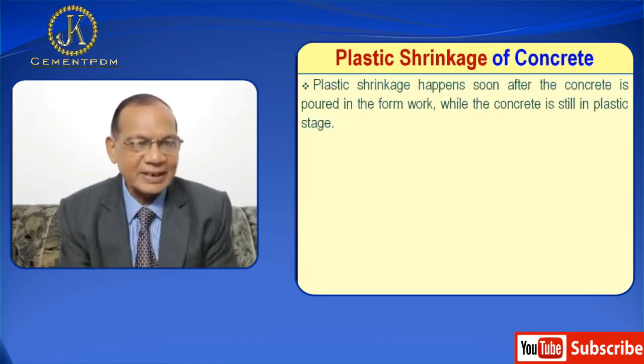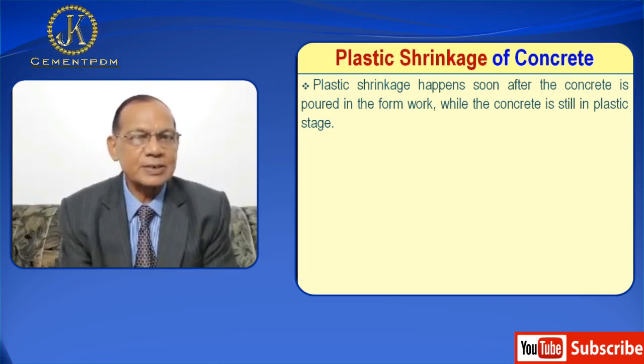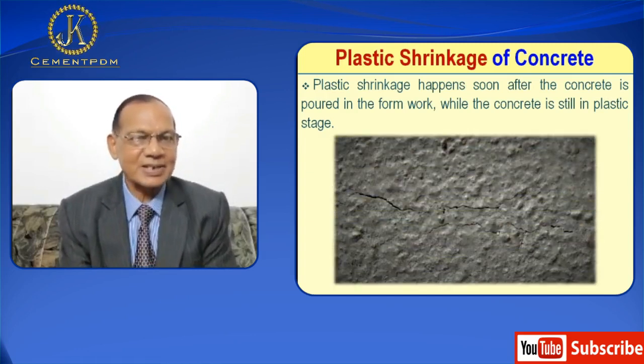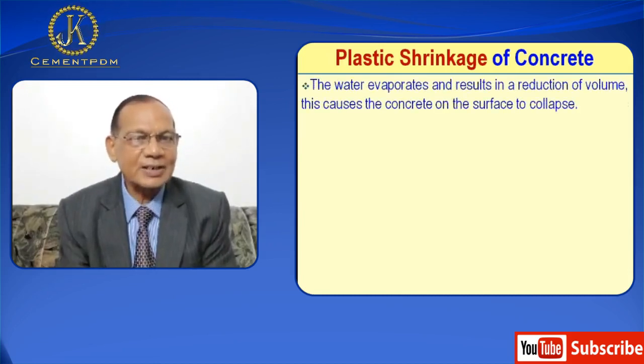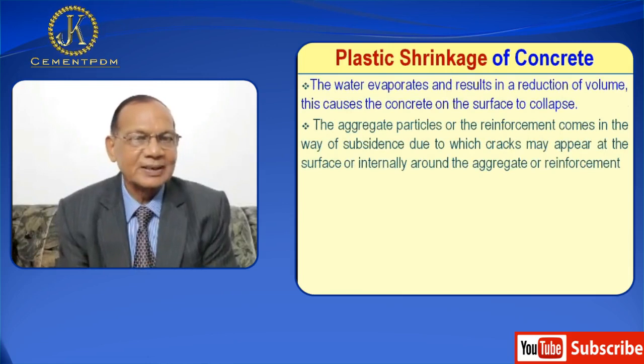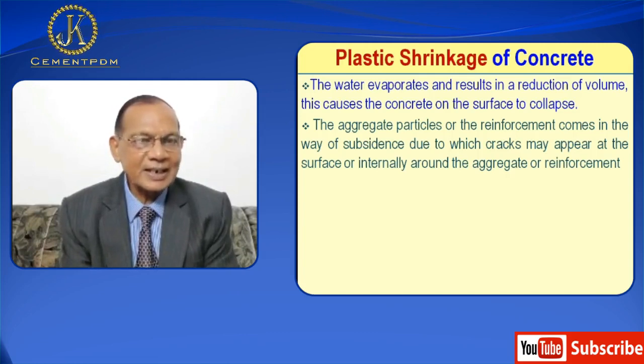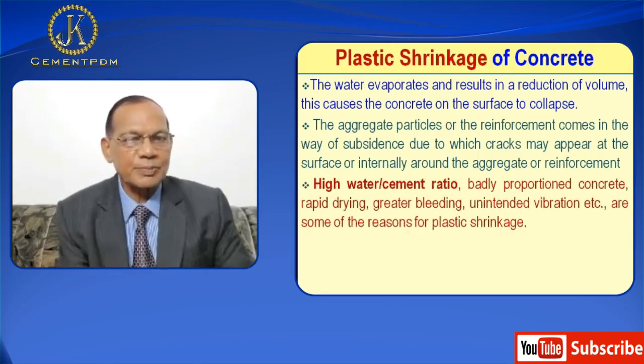Number 1, plastic shrinkage. Plastic shrinkage happens soon after the concrete is poured in the formwork. While the concrete is still in plastic state, the water evaporates and results in a reduction of volume. This causes the concrete on the surface to collapse. The aggregate particles or the reinforcement comes in the way of subsidence, due to which cracks may appear at the surface or internally around the aggregate or reinforcement.